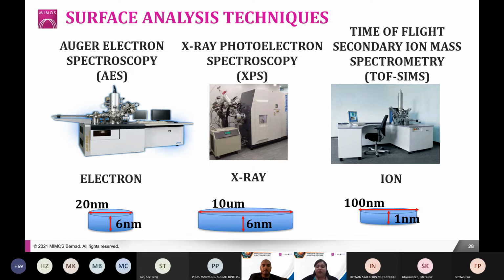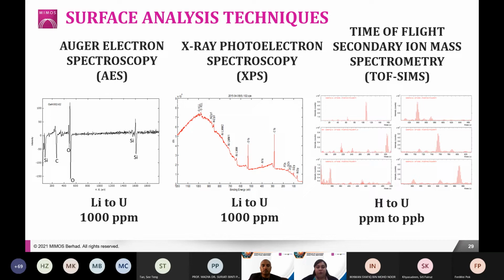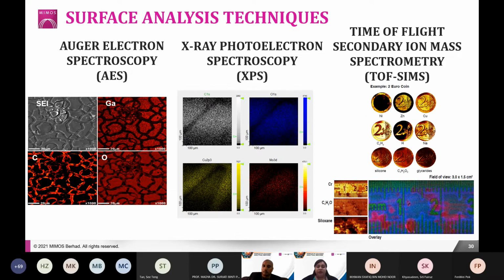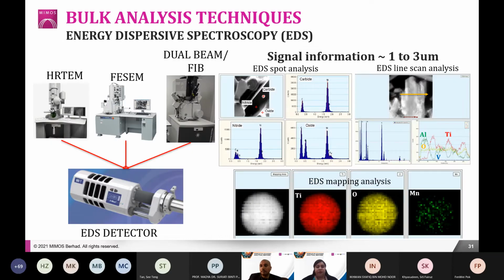Same goes to XPS, but the depth is higher, about 10 micrometer, and they're using an X-ray source. And for TOF SIMS, we're using an ion source with a 1 nanometer depth, so it's very, very shallow. Okay. And then, what are the elements which we can detect? For AES and XPS it is from lithium to uranium in parts per million. Whereas for TOF SIMS, we can detect from hydrogen to uranium, from parts per million to parts per billion, right? And this is the type of mapping which we can obtain from this particular equipment as well, right?